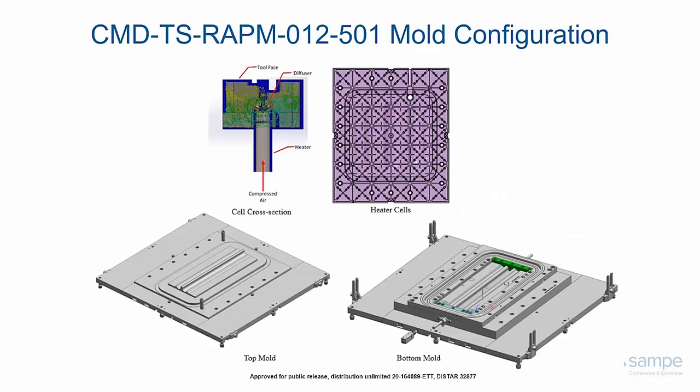It's important to look at the actual molding tool used on the PTFS clamping fixture — specifically the bottom mold and the top mold. This tool was designed for the Surface Generation machine using a pixelated tooling heating approach, which allows you to tailor the temperature of certain areas if you have thicker or thinner laminate sections. This tool is a closed-cavity tool, meaning no resin escaped out the sides. We also had the ability to pull vacuum, apply thermocouples, and eject pneumatically or mechanically as needed.